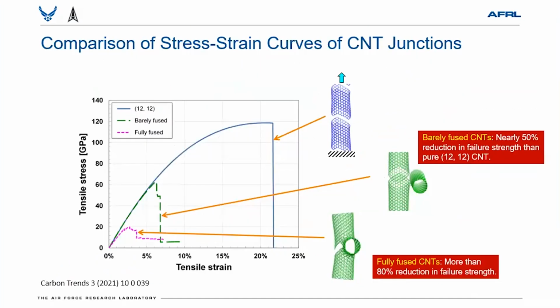That's not the case. Reason being, when you are fully fused, you are destroying the nanotube integrity, hence its load carrying capability, as compared to barely fused, where you retain as much of the bond integrity within the carbon nanotube, or atomistic configuration, than the fully fused.